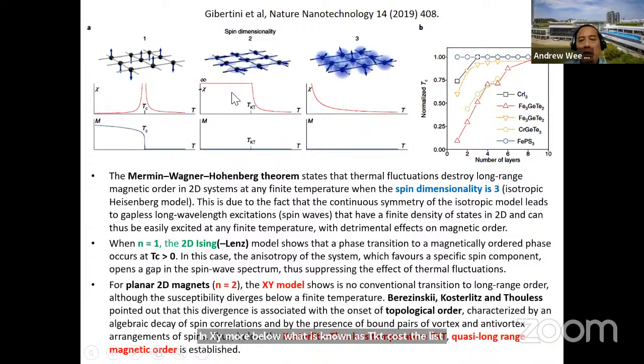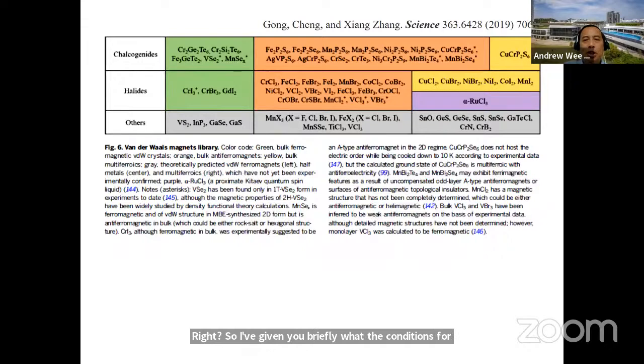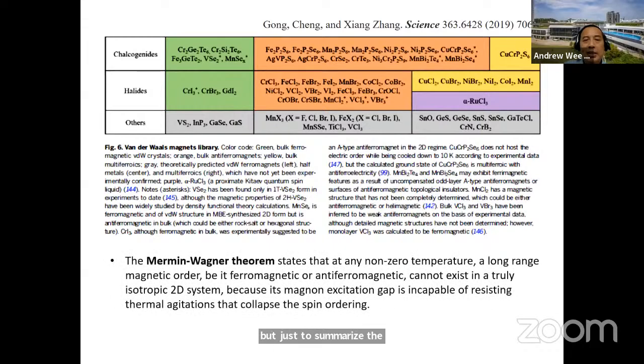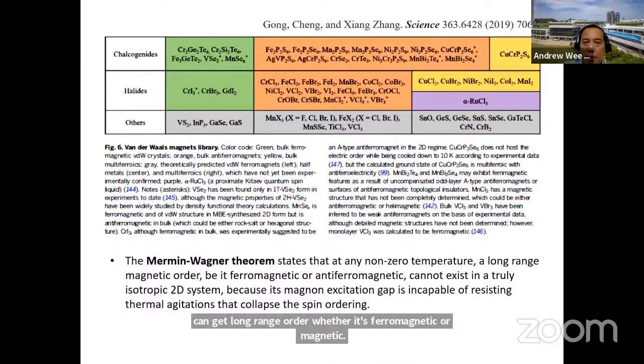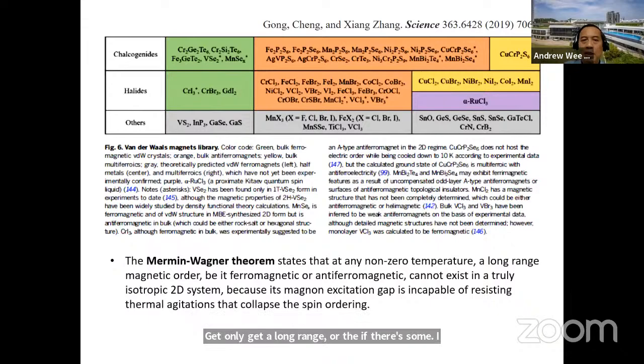Right, so I've given you briefly what the conditions are for obtaining a 2D magnet. But just to summarize, the Mermin-Wagner theorem says that at any non-zero temperature, you cannot get long-range order, whether it's ferromagnetic or antiferromagnetic, in an isotropic system. You can only get long-range order if there's some anisotropy in the system. Because in an isotropic system, the magnon excitation gap is incapable of resisting thermal agitations that collapse spin ordering.